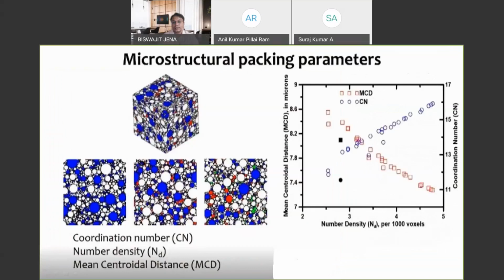So next, microstructural packing parameters. We did some computational work, and again, this does not have to be computational if you know what you are using, but we wanted a wide range of materials so that we can start looking at packing of all these materials in different spaces. If you see the bottom leftmost picture, it has only two sizes of particles, the cement and fly ash. If you go to the next one, I have introduced another size of particles in red, maybe that is metakaolin. If you go further down, I have green particles that may be limestone. So as I sequentially increase the number of particles and change the size of particles, I get completely different packing.